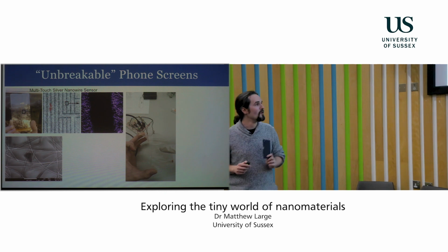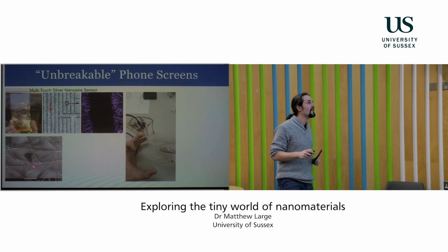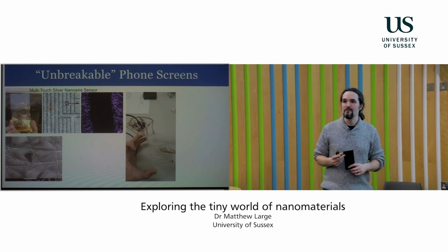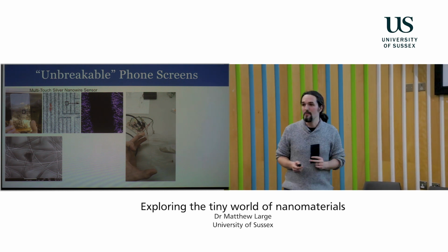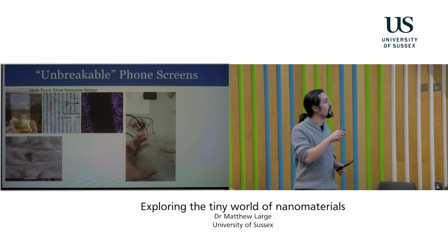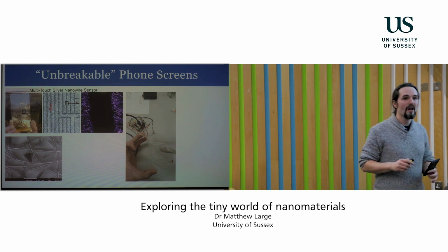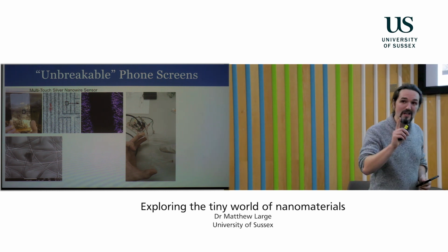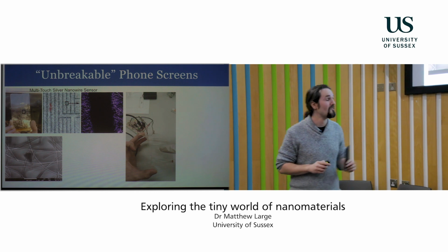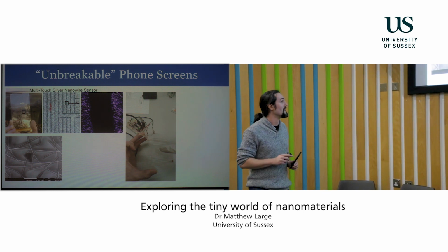So what we found that we can do, and you saw this image earlier, is we can add tiny quantities of graphene to replace some of the silver. We put down less silver, we put our graphene film on top, and this produces something which is more conductive than either material on their own. And this is a very clever trick, which we discovered completely by accident.